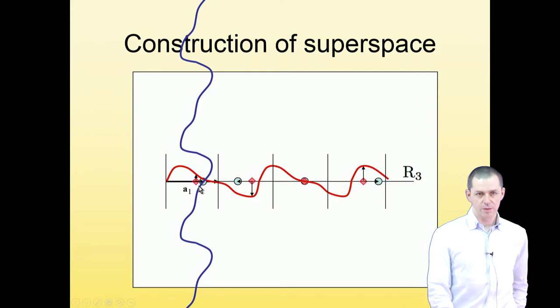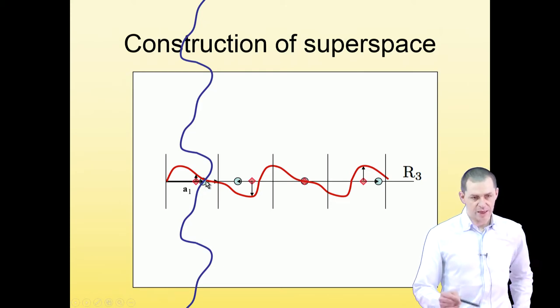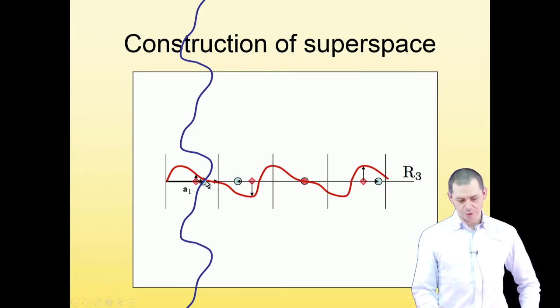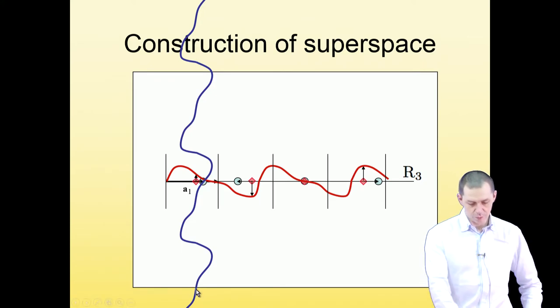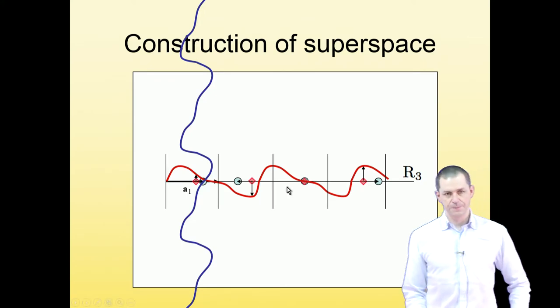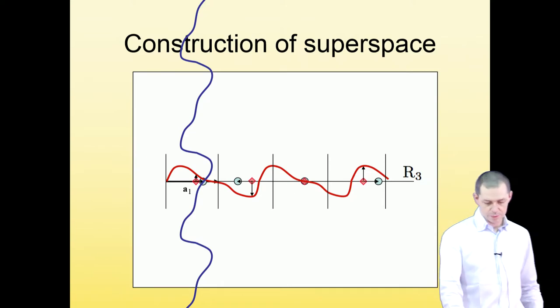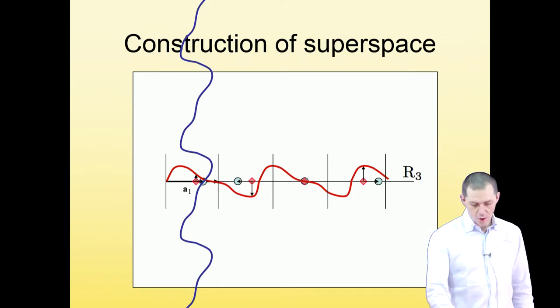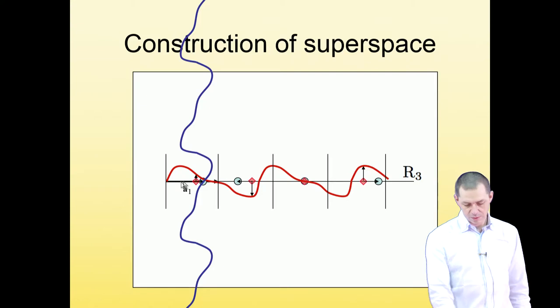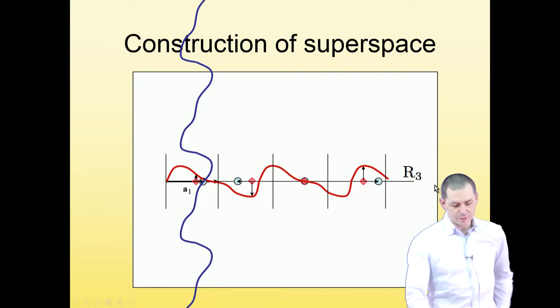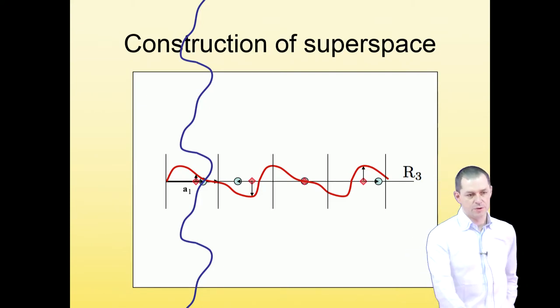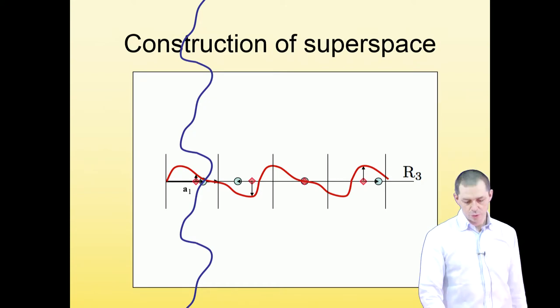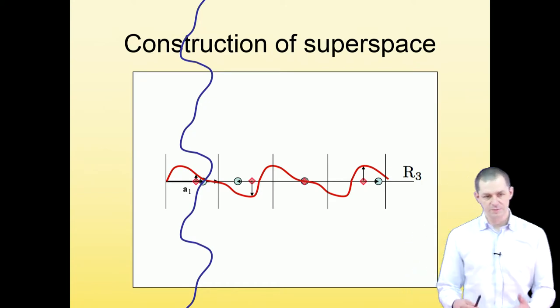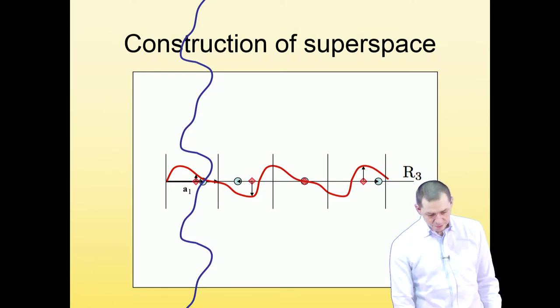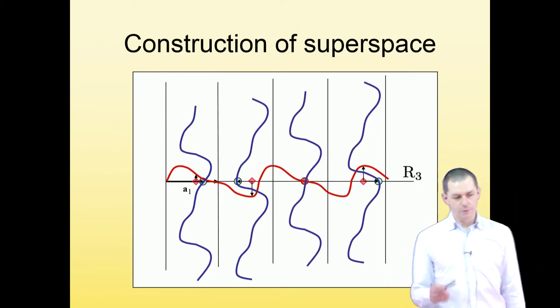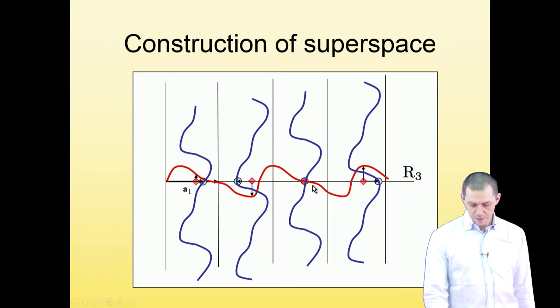Now the modulated position of the atom is actually really given by an intersection of this line, of the blue curve, with real space. So we obtain the modulated position as an intersection of the modulation function with the real space. But we had to add a new dimension which goes perpendicular to the real space, to the physical space. And then we do this for all atoms, for every atom in each unit cell.